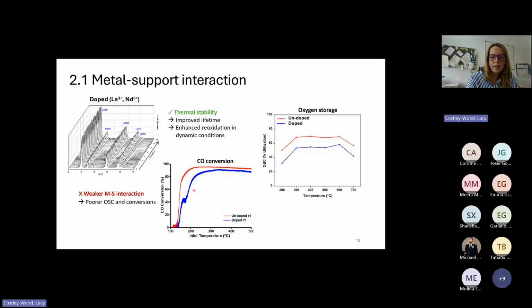It also explains why we have this activation, because when we start the CO conversion, we believe that the part of the catalyst that's doing most of the work is just the palladium. And it's only after this activation period under slightly reducing conditions at 200 that the oxygen is able to be released from the ceria zirconia via the palladium in that redox couple mechanism. So after that point, we're able to operate in this Mars van Krevelen mechanism.